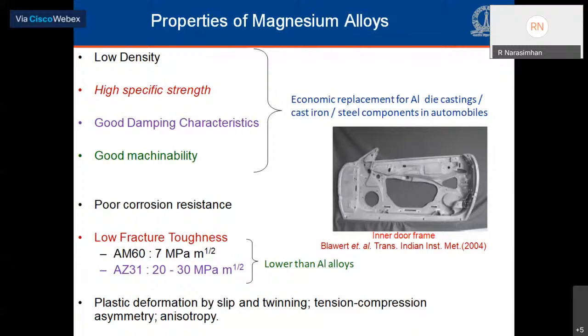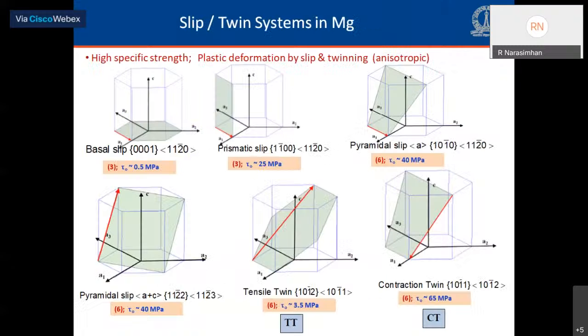Another very characteristic feature of magnesium is that, being an HCP metal, it doesn't have an adequate number of slip systems to accommodate arbitrary deformation. So therefore, plastic deformation happens by a combination of slip and twinning. It's highly anisotropic. And one of the manifestations of that is tension compression asymmetry. At room temperature, magnesium has 18 slip systems and 12 twin systems. I have shown that in this slide, and I've also indicated the number of systems per type, as well as the critical resolved shear stress pertaining to each of these systems underneath